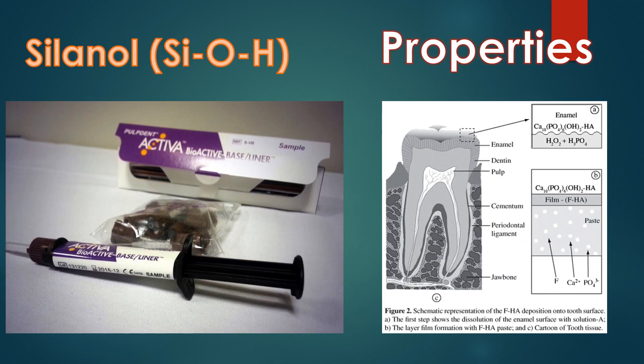Bioactive glass has two main properties: bioactivity and antimicrobial properties. Once in contact with body fluids like saliva, bioactive glasses immediately undergo ionic dissolution and glass degradation via the exchange of hydrogen ions in the solution and sodium and calcium ions from the glass network. The ion exchange results in the formation of silanol groups due to the hydrolysis of silica groups. An increased alkaline environment then develops because of the rise in hydroxide concentration. The silica network is further degraded as the pH rises, forming orthosilicic acid and silanol groups on the surface in the form of a negatively charged gel. This gel layer functions as a matrix for hydroxyapatite deposition.